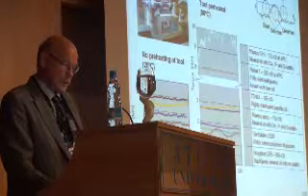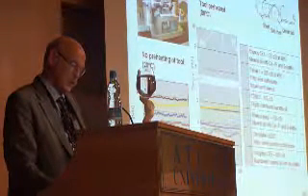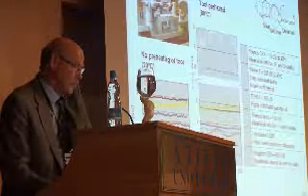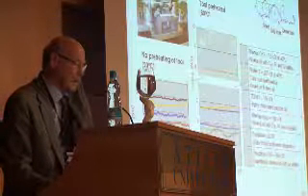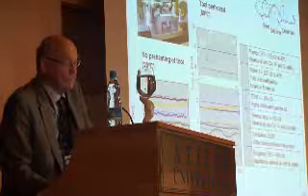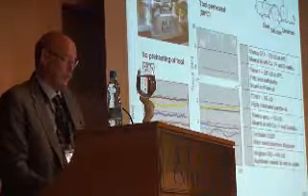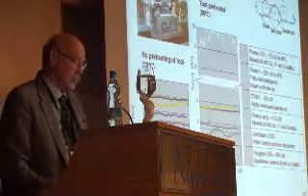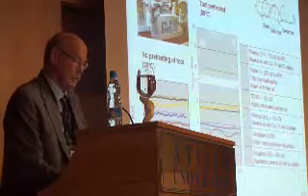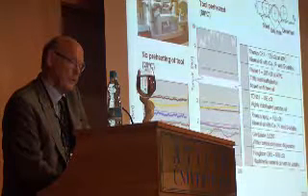Houghton. Sorry, the colors are not shown here for some reason. But this is the plain mineral oil, the white curve. The heating to 80 degrees implies that all lubricants work fine again with somewhat higher friction, but still low, except for the plain mineral oil, which breaks down immediately. So the testing temperature is vital for the lubricant behavior.